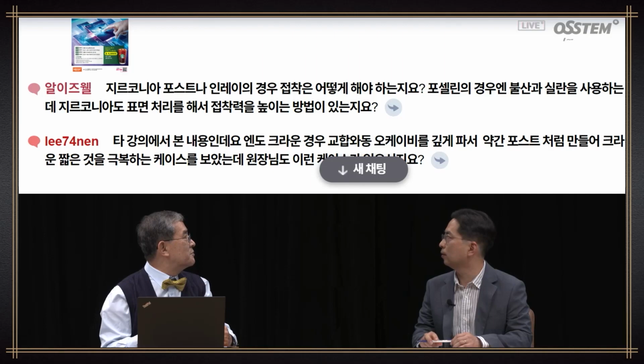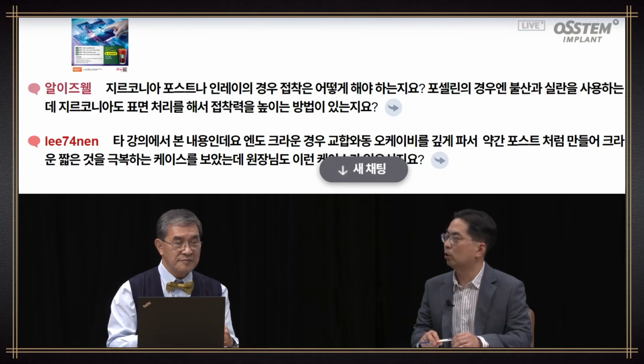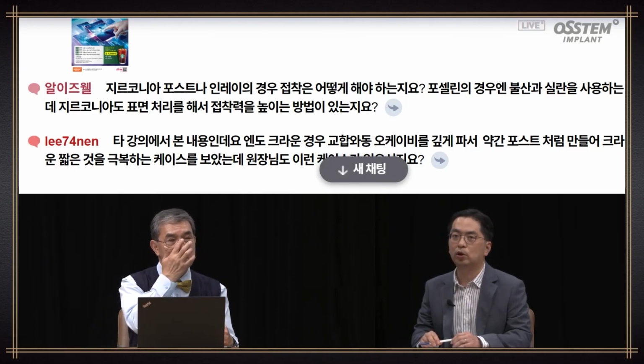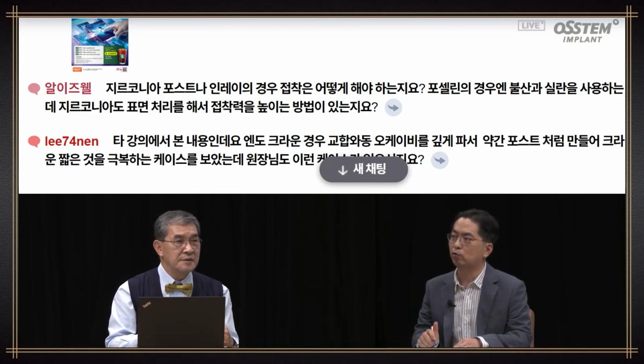All is well. In the case of a zirconia post or inlay, how do you do bonding? In the case of porcelain, you use hydrofluoric acid or silane. Do you do any special surface treatment for zirconia to increase bonding? There are zirconia adhesives. Most adhesives contain MDP monomer. Chemical bonding can be achieved.